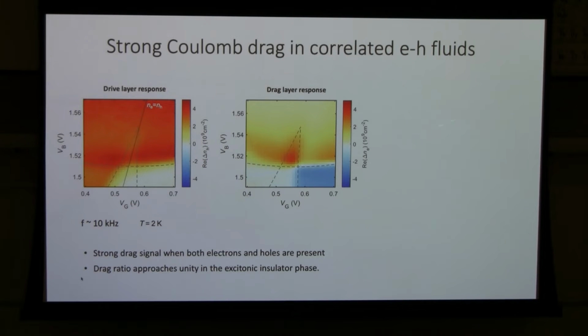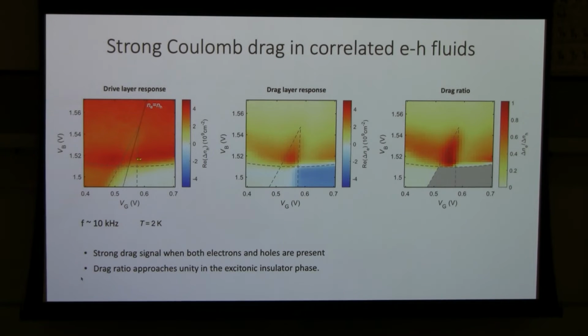But things become completely different when you have both electron density and hole density. In that case, the hole density change and the electron density change actually have the same sign. So that means you actually have a pretty strong drag signal in all of this phase diagram. And this drag signal is particularly strong within this triangle region. If we do a ratio between the hole current and the electron current, we can actually find the drag coefficient is almost 1 over here.